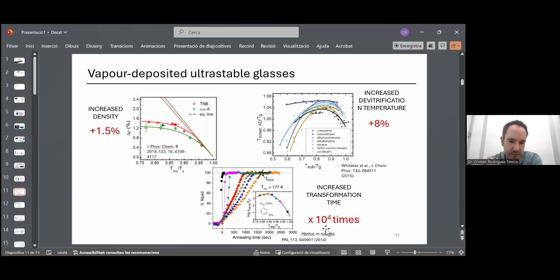So in fact, it is approximately the same for all materials, 10 to the 4 times larger than the time that the ordinary glass would take to go from the glass to the liquid. For a conventional glass, if we go to Tg, it's considered that the relaxation time is 100 seconds. In this case, if we take the ultrastable glass, again at 85% of the relaxation temperature, we have almost 10 to the 4 times, okay?